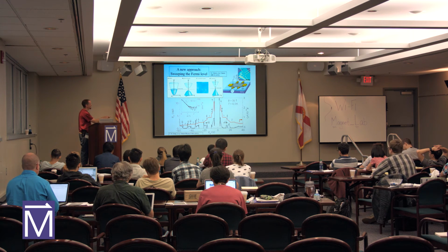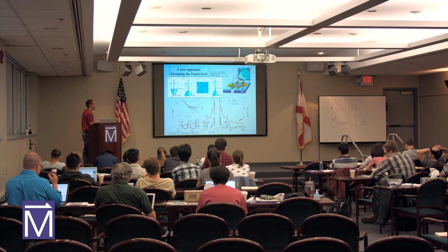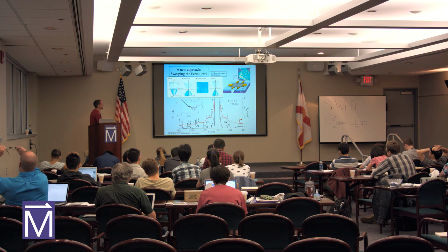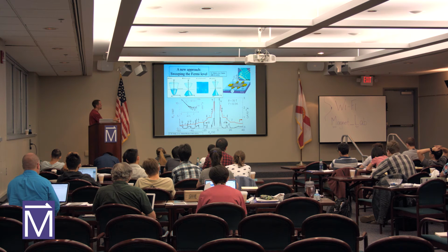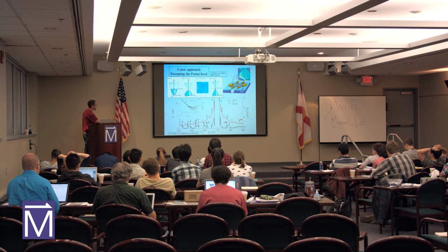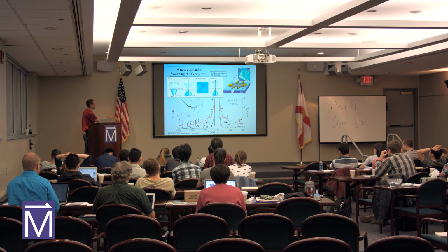So graphene has this kind of linear dispersion relation. For what we're discussing, we'll just say that means it has a low effective mass. But what we can do with this gate behind the sample is apply an electric field across the sample, and that'll shift the Fermi level. Okay, so we can do conventional transport measurements like shown in this inset. We have a sweep up to 2-point-something Tesla, but we see quantum oscillations by measuring RXX. That's the resistance along the sample.